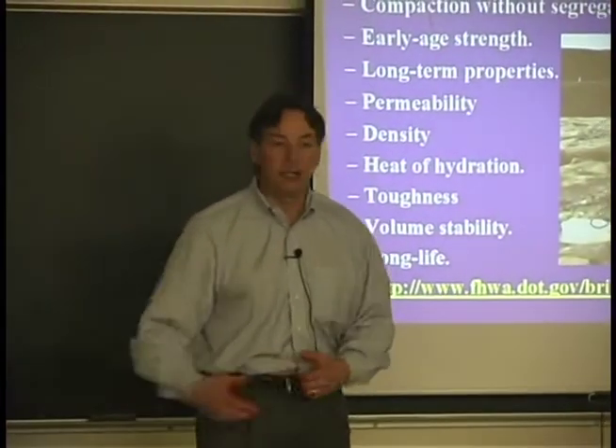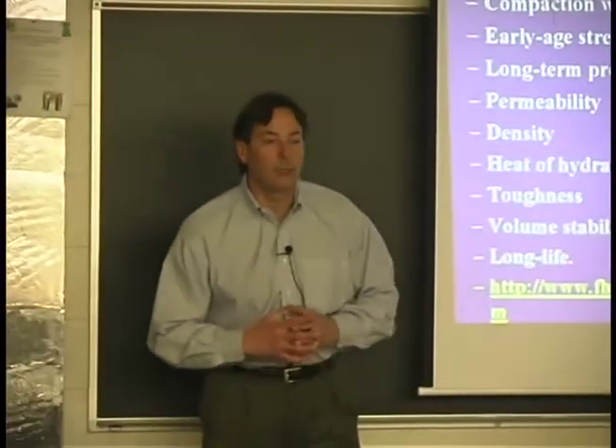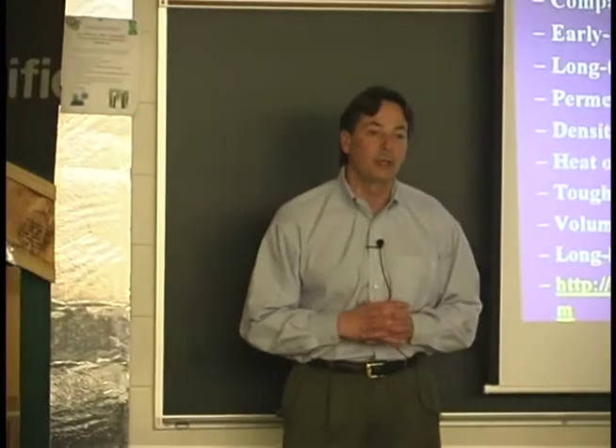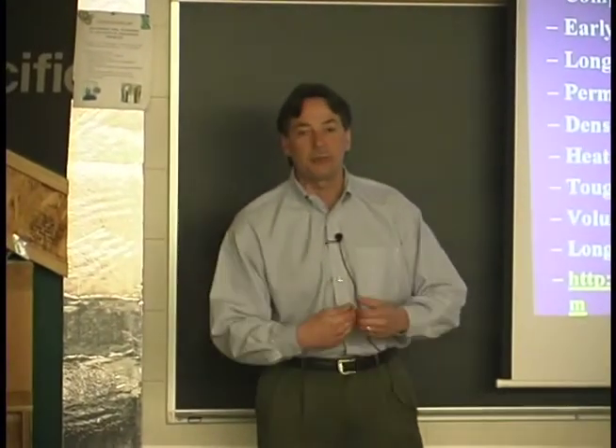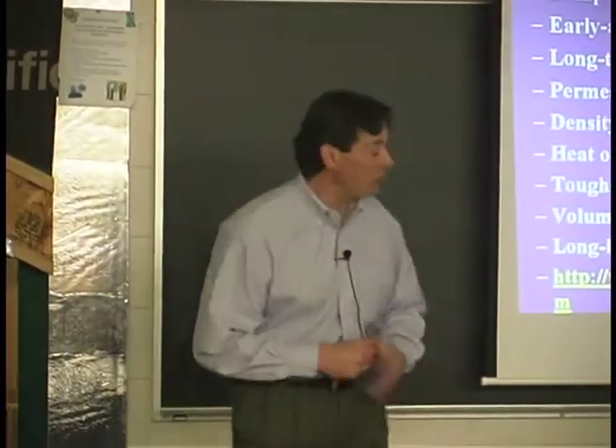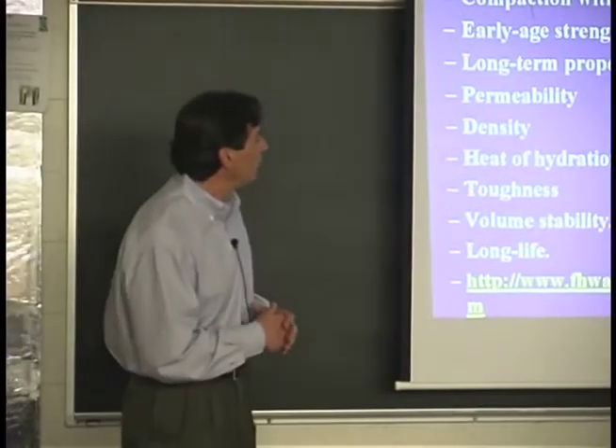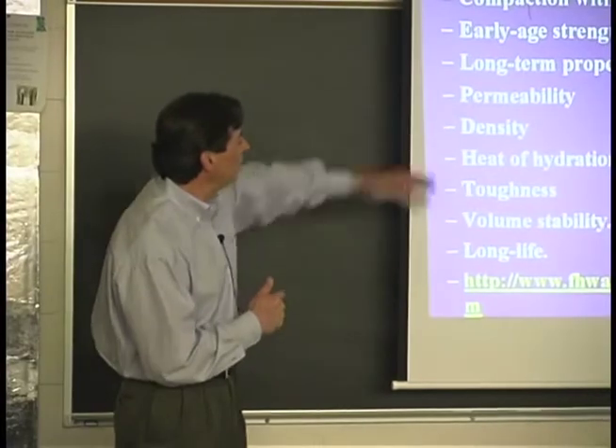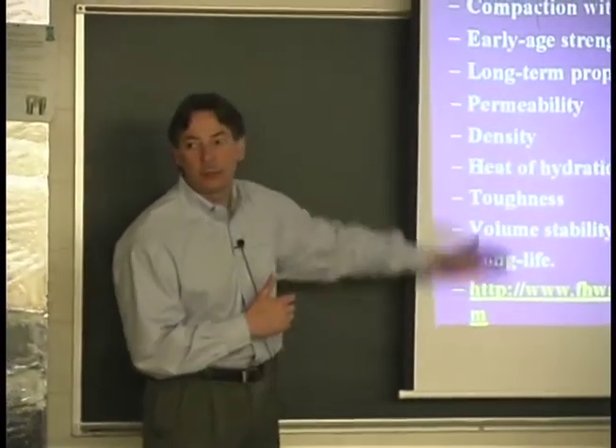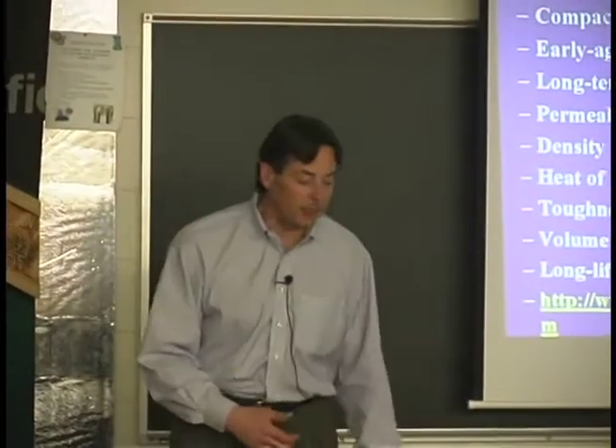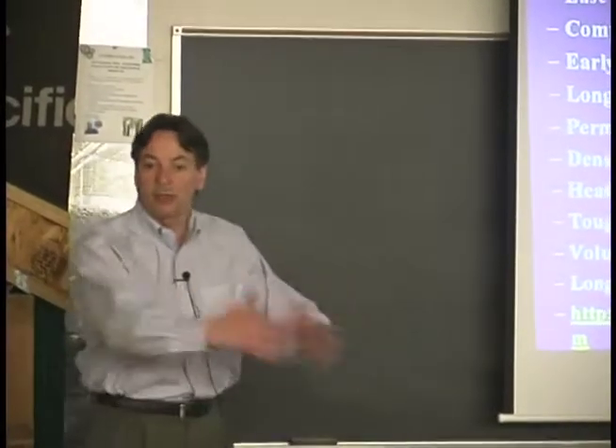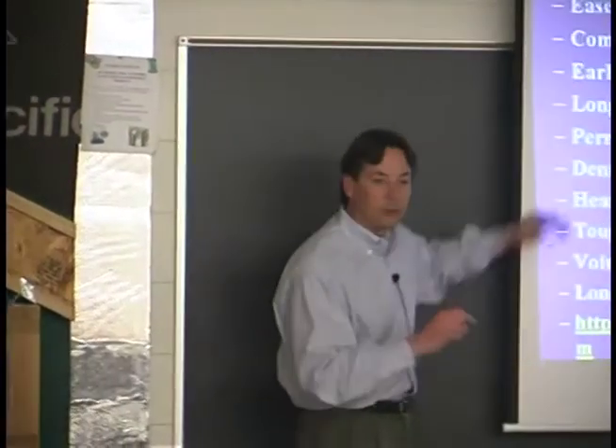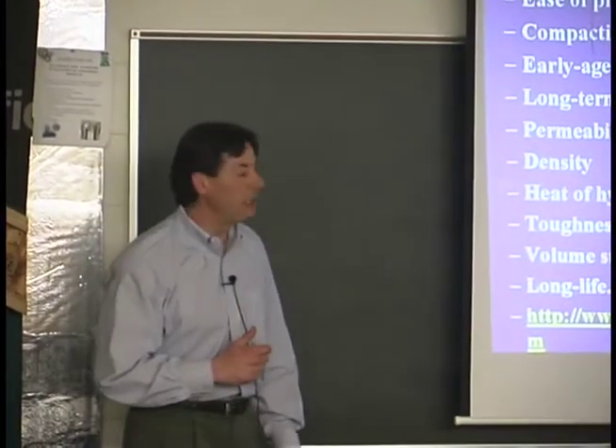In a precast plant, they've cut labor, probably 80% in the last 6 years. They don't have to vibrate the beams, and they get much better finishes on their concrete. But that's just one area of what would be a characteristic for a performance. Early age strength, if we wanted to fast track, if we wanted to rebuild an intersection, we wanted to get on it and off of it in 4 hours' time, you can do that. There's concretes that you can tweak that characteristic and make it happen.